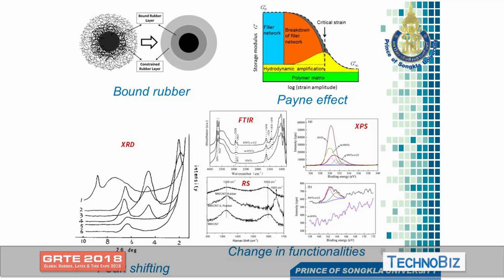Once the reinforcement is there, normally we have to investigate the reasons behind the reinforcement. So normally we check the bound rubber content. The more bound rubber content, that means there are rubber-filler interactions. So we normally study the rubber-filler interactions in order to support the research findings. Another thing is the Payne effect. Normally, in this kind of study, we vary the strain amplitude, the strain rate. Once we apply high strain, we see whether the filler network is there or not. If the rubber-filler interaction is there, the difference between the storage modulus at lower strain and higher strain will be reduced. The small difference means there is high rubber-filler interaction.